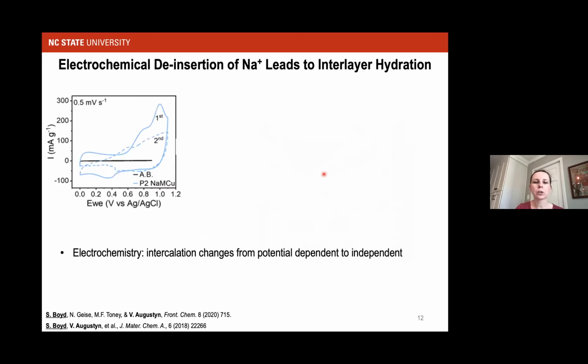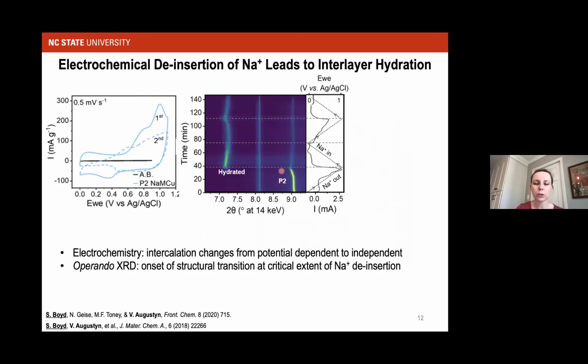What was the mechanism taking place? What we found using operando X-ray diffraction is that these materials undergo essentially a first order phase transition to a hydrated structure when some critical amount of sodium is removed. So here's a cyclic voltammogram again, showing this big distinction between first and second cycles, potential dependent, then more potential independent. What we see from the operando X-ray diffraction is that sodium is removed from the structure. We see this P2 phase maintained until you get to a critical amount of sodium deinsertion, and you have this phase transition that occurs very suddenly.